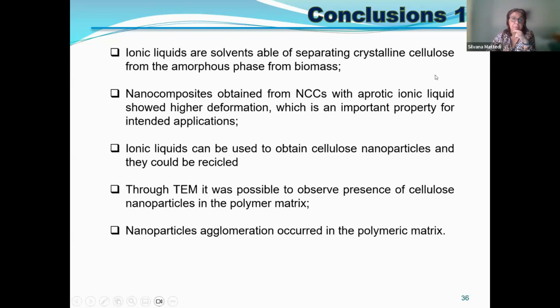So ionic liquids are able to separate crystalline nanocellulose from the amorphous phase from biomass. The nanocomposite with sulfuric acid, with the aprotic ionic liquid, shows the higher deformation, so the elongation is better. So it's an important property if you want to make films. Ionic liquid can be used to obtain cellulose nanoparticles, and they could be recycled. We tested the recyclability, so this is very interesting, because one main problem with sulfuric acid is that you cannot recycle it.